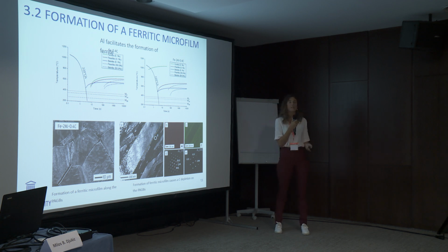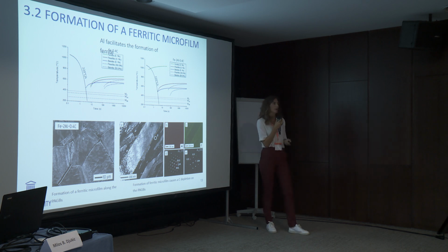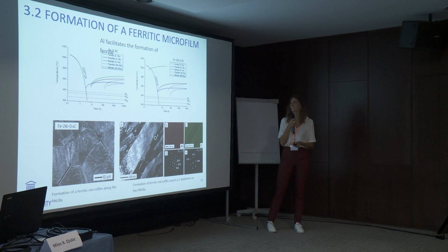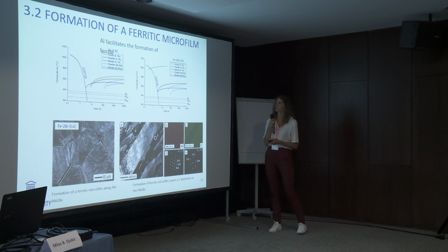Why does it have a carbon depletion? Well, if you quench your austenitized steel, the first thing you form is this ferrite, and parent austenite grain boundaries are mostly the nucleation sites for phase transformation. And since the carbon solubility in ferrite is much lower than the surrounding austenite, your carbon is pushed out. So this also results in carbon depletion.